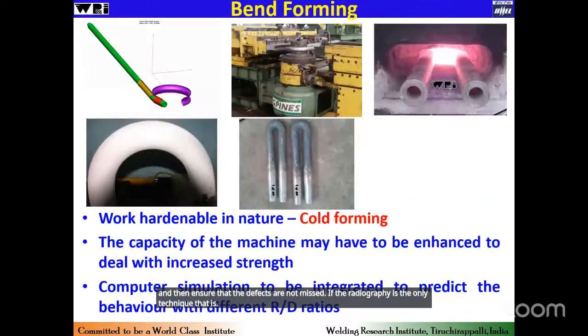And not just that, even with radiographic inspection, it is not going to be the same as what we see in the case of steel, because of the difference in the absorption coefficient. The steel equivalent of nickel is 1.3. The other problem is that nickel oxides are difficult to detect, the oxide inclusions, especially when they are thin, and most of the oxides, especially with the GTAW processes, are thin and oriented parallel to the surface. So there is a chance that we miss it. So we have to take radiographs at different orientations and ensure that the defects are not missed if radiography is the only feasible technique.